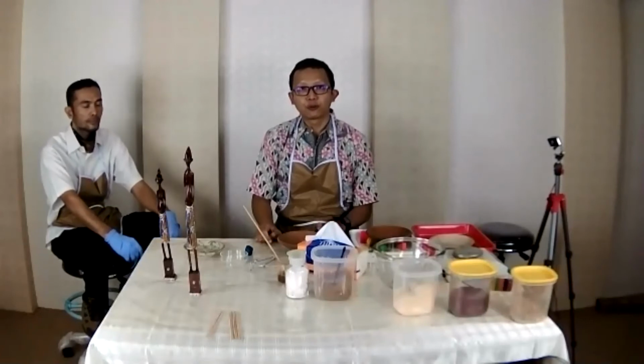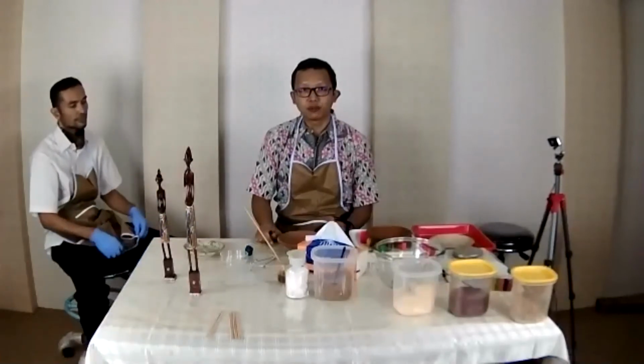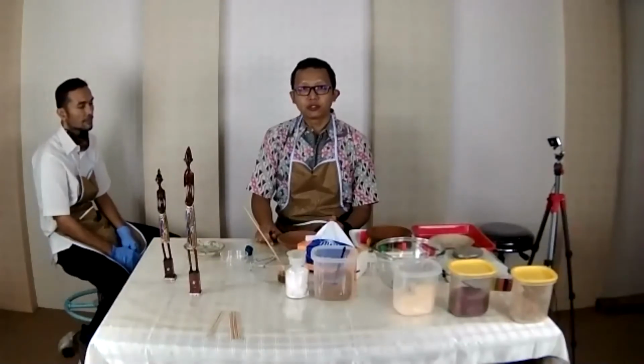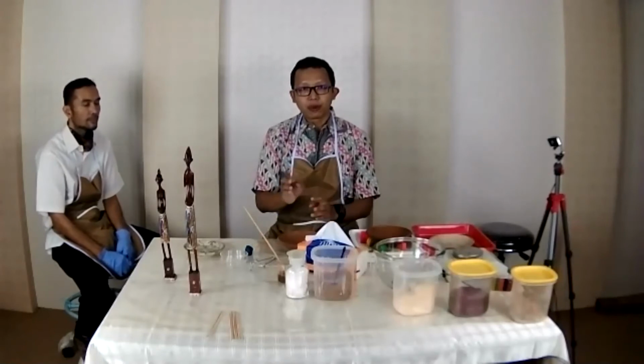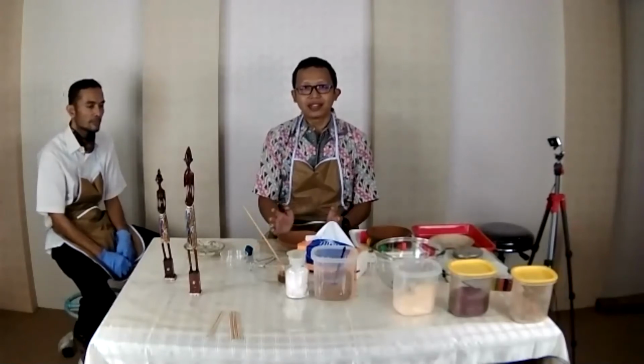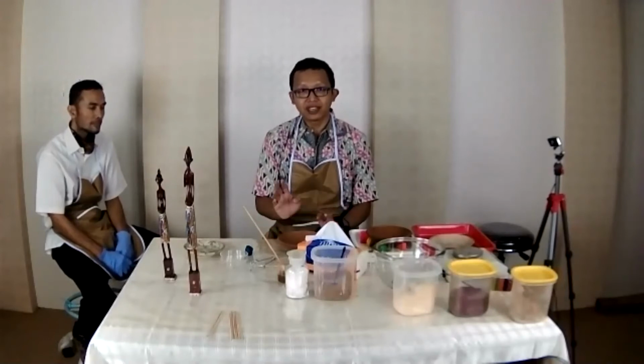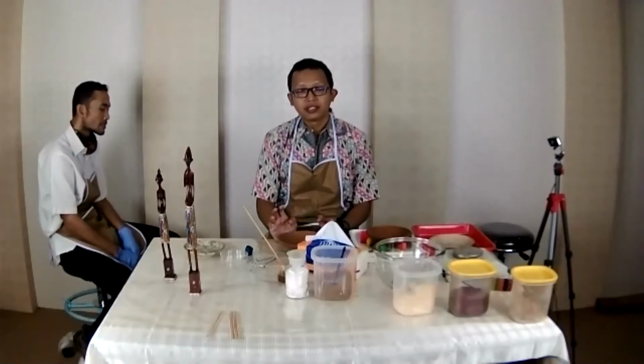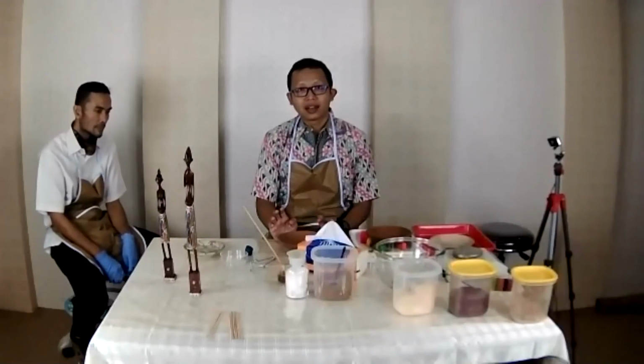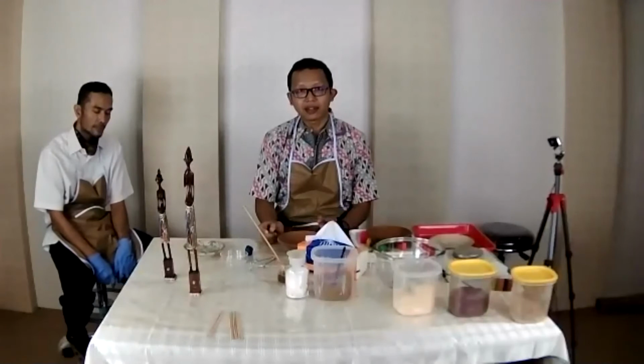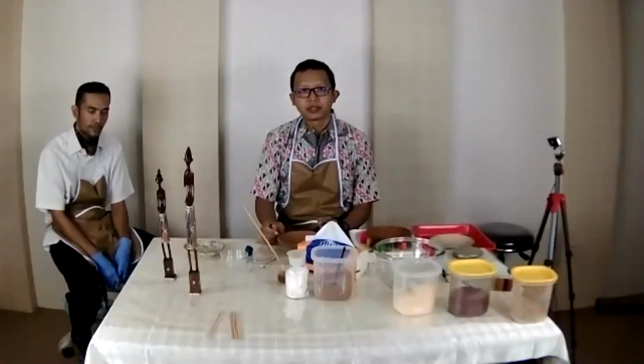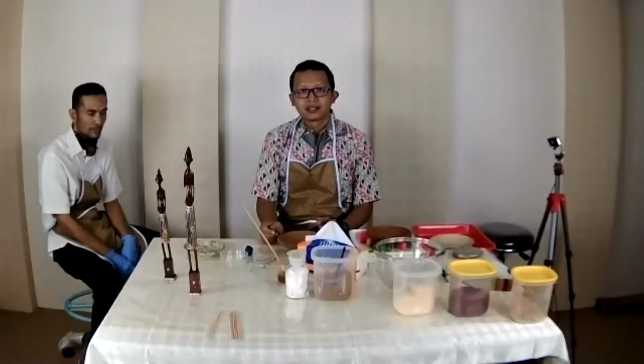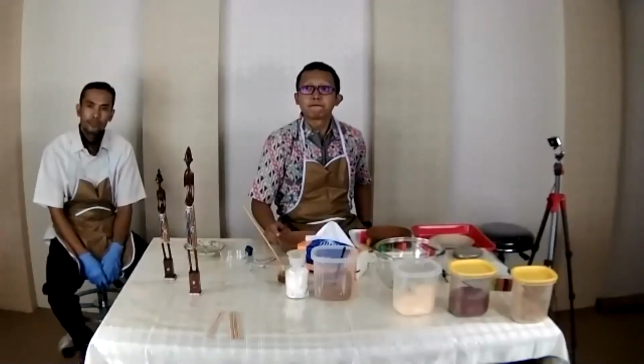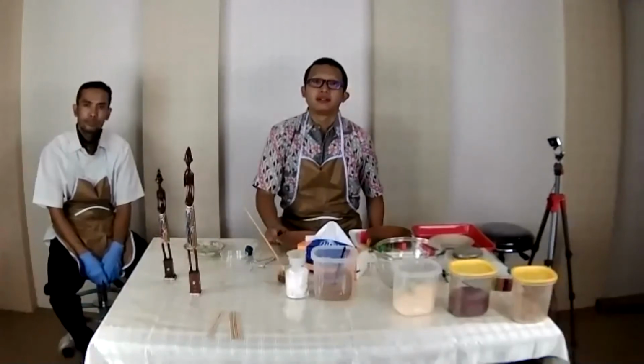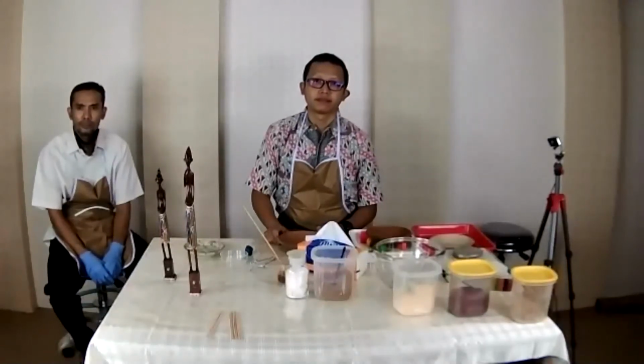If we know that the humidity in our museum is stable, so there's no high fluctuation between the humidity during the day and the night, then if you want to turn off the aircon, do not turn it off. It just has to be turned on continuously to maintain the humidity level. This is to keep the humidity fluctuation minimum. So that's probably what I can answer. Thank you very much.